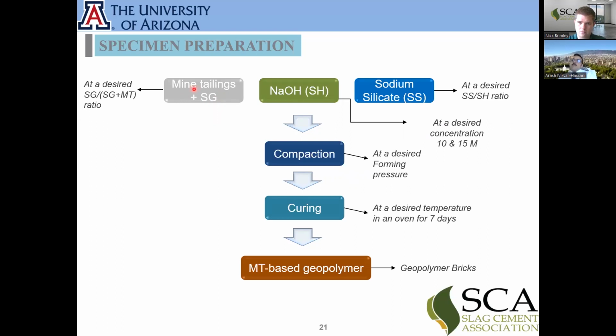So the maximum amount of the ratio went toward the mine tailings. Then we mix this combination with sodium hydroxide as alkaline activator. Then we added some sodium silicate to balance the silica and alumina ions. Then we mix them and compact them inside the mold. Then we cure them in the oven. And at the end, we have the bricks. And we did the testings on the brick samples.